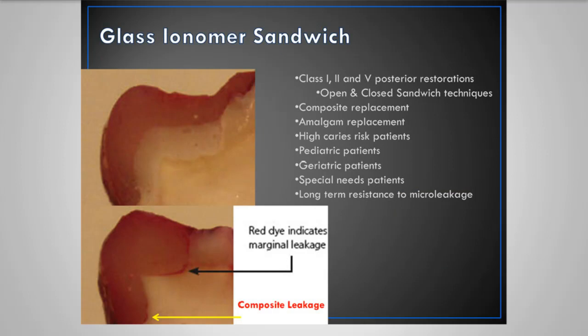So when looking at this glass ionomer sandwich technique here, you notice the top one, the top image, shows the glass ionomer underneath as this white area, and the composite being on top is red. So the dye penetration study showing the composite having microleakage over time, you'll notice that this dye adapting here at the marginal areas where the composite has actually pulled off the preparation design, allowing for space here and microleakage. The microleakage is shown as the large amount of dye there.